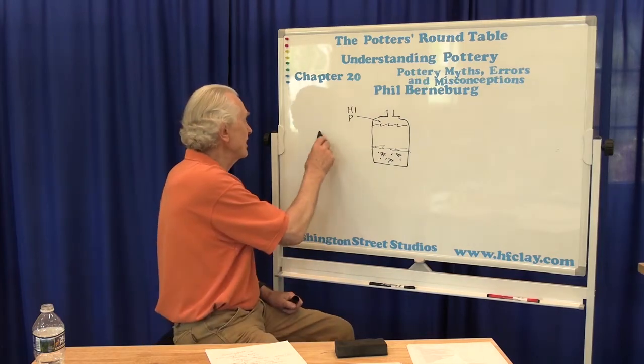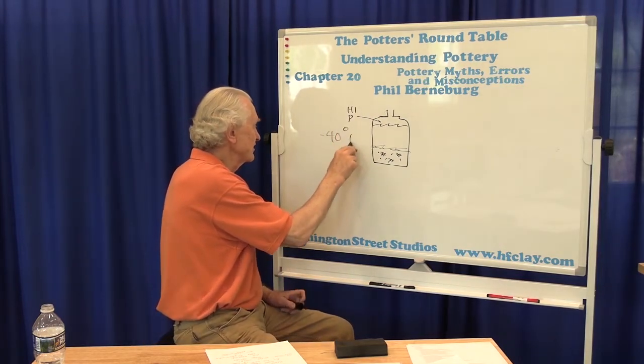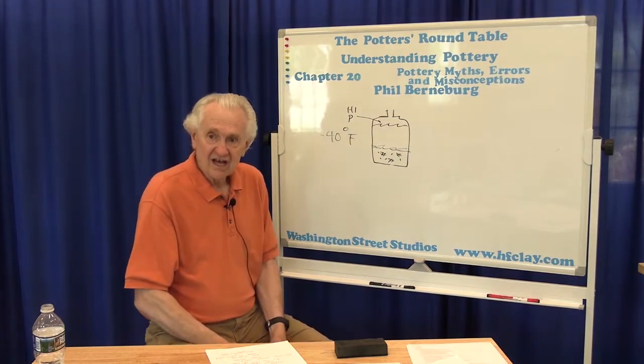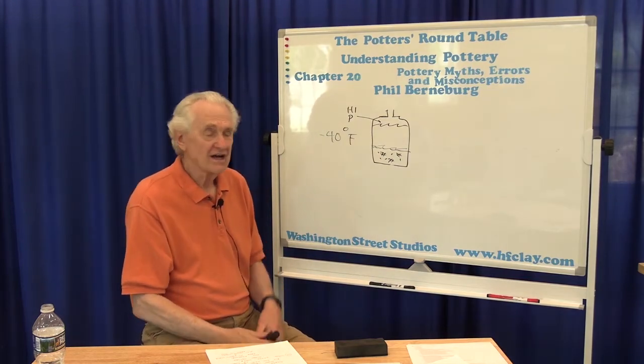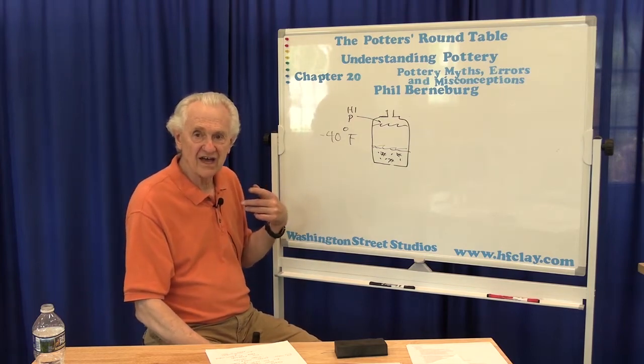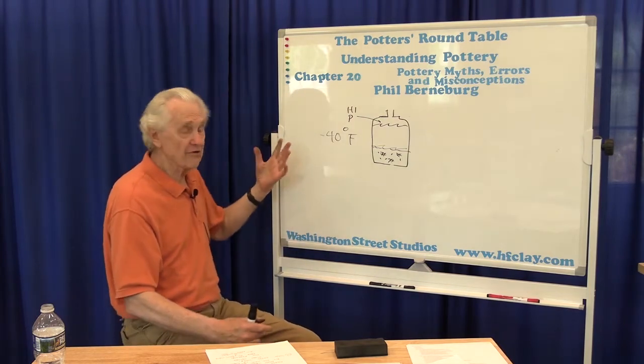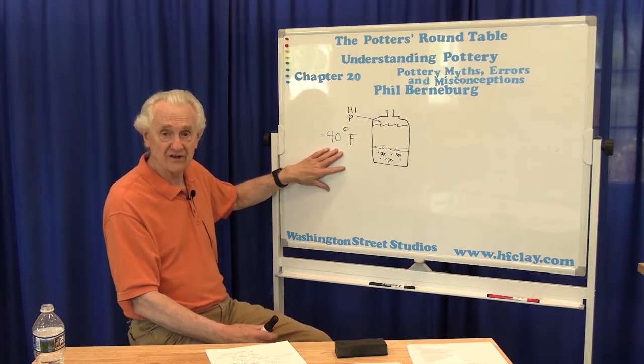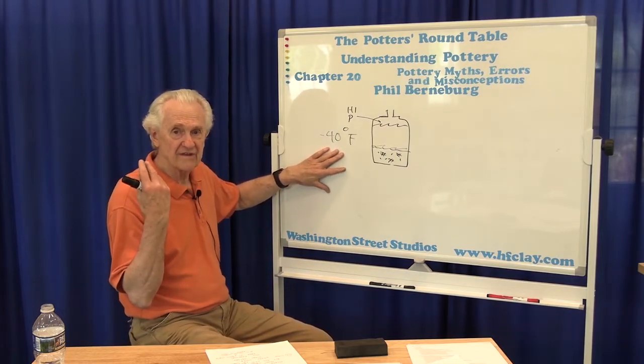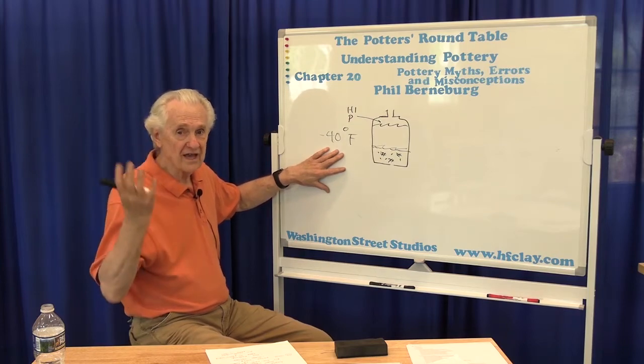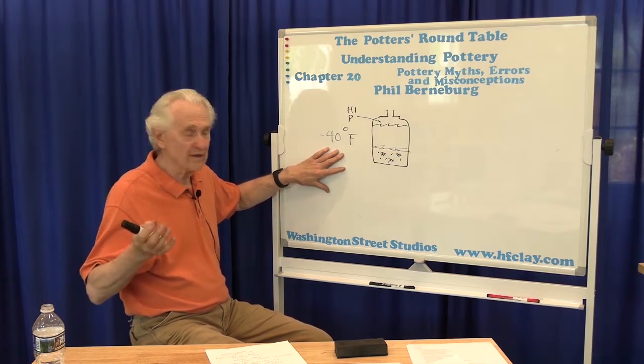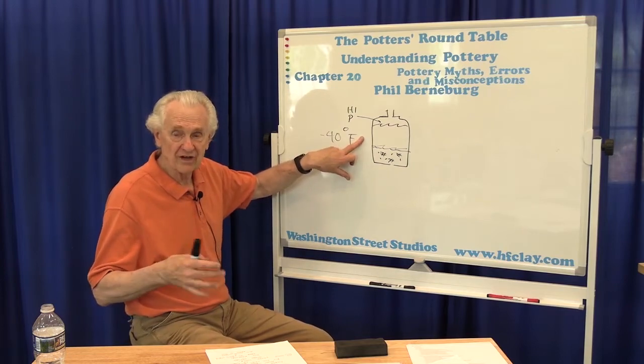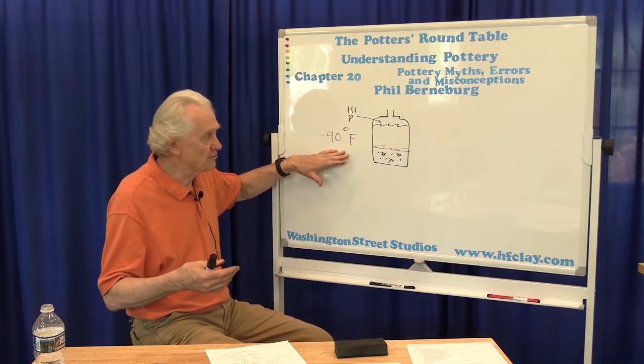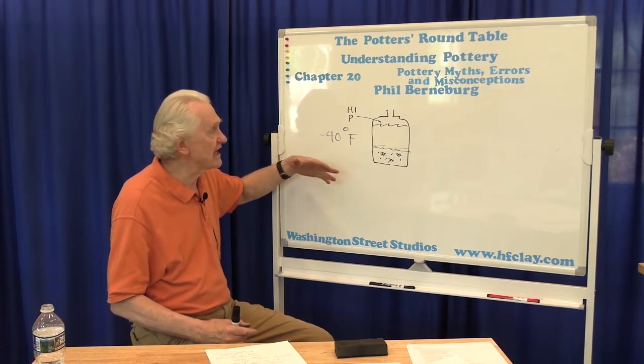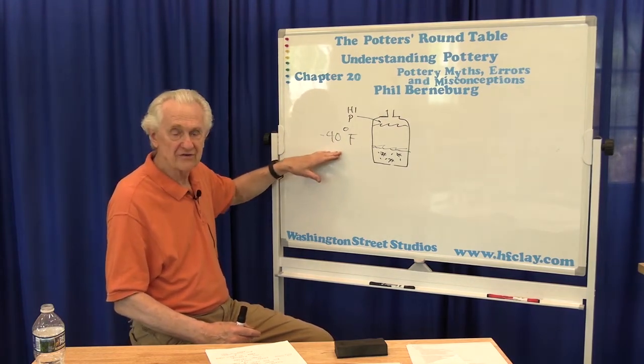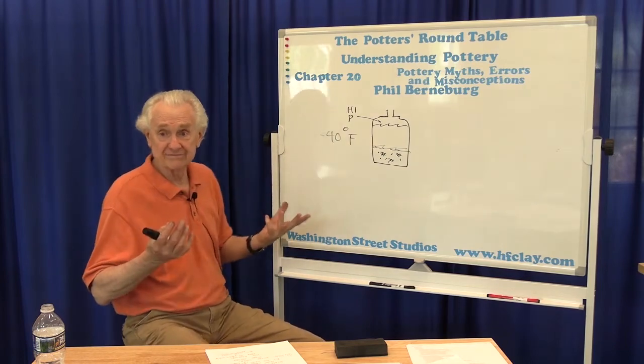By the way, normal propane boils at 40 degrees below zero. So this means that unless you're living in Alaska or Antarctica, when you put a propane tank outside, you're going to get propane gas out of it. Now, if it was, let's say, 50 degrees below zero, and I put a propane tank outside and opened the top, nothing would happen. No gas would come out, basically, because the propane wouldn't boil, because it's going to stay below the boiling point. A little bit would come out, but not much. So the reason why it makes a lot of gas is because anything above 40 degrees below zero is hot enough to create a lot of boiling.